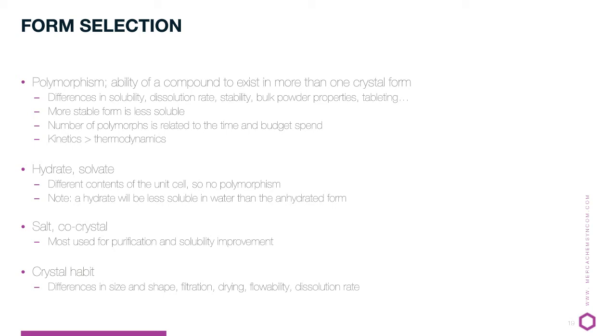When you look at hydrates and solvates, these have a different unit cell, so it's not a polymorph. It is a hydrate or a solvate. It consists of different parts in the unit cell. Selection of a stable hydrate might be preferred above one of the most stable anhydrous forms, because we have to take into account that the hydrate will be less soluble in water than the anhydrated form.